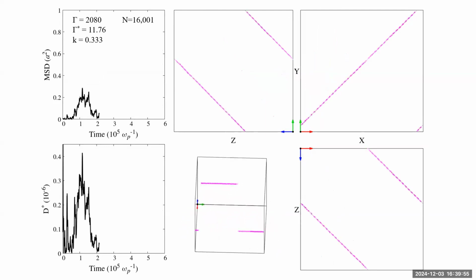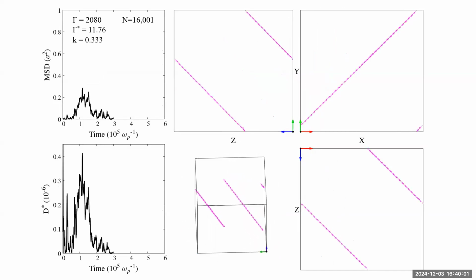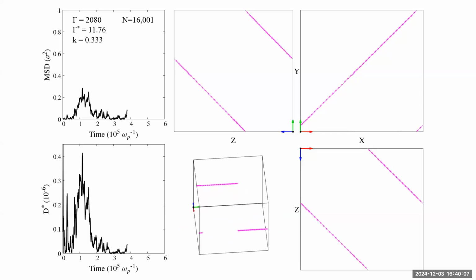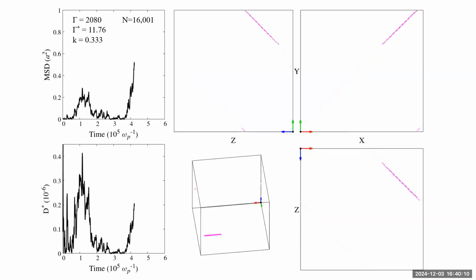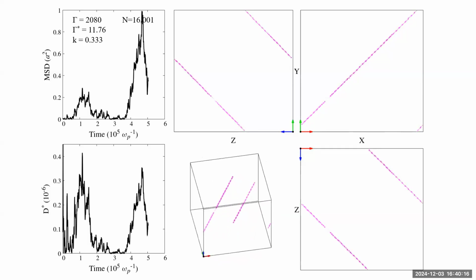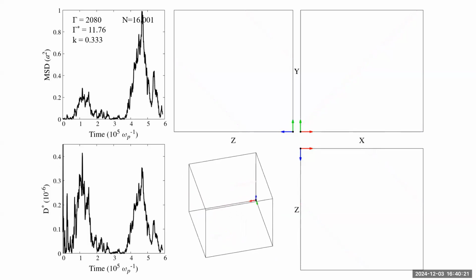This is a one-dimensional random walk. It goes forward, and then it goes backwards, and then it goes forwards, and maybe goes forward for a while, but eventually it turns backwards. And anybody who knows the dynamics of a one-dimensional random walk knows that it always comes back to the origin. Oh, look at this. Yeah, it's going really far in one direction right now. And oh, look, that's inflating my diffusion coefficient. But as soon as it ends up back where it started, it ends up undoing all of those diffusive hops. So it's like you've taken a stack, you've moved it forward, but then eventually you move it back. Or you move it so far forward that it comes over the periodic boundary and you move it back into place anyway. So the diffusion coefficient is garbage here. You can't actually extract a diffusion coefficient this cold, even though you see diffusive hops.